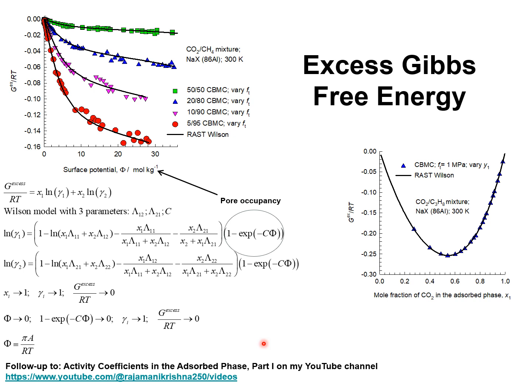The carbon dioxide guest molecules tend to congregate around the extra framework cations, and there is an inhomogeneous distribution of guest adsorbate within the Faujasite topology of sodium X zeolite that consists of cages of 11.5 angstrom in size. Each cage is separated from an adjacent cage by windows that are 7.4 angstrom in size.